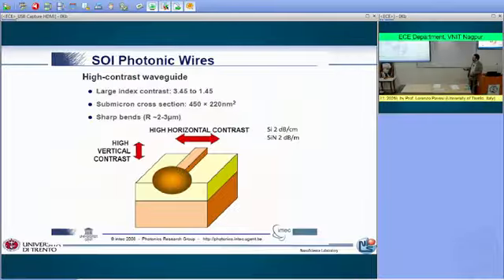Sidewall losses scale with the refractive index contrast. Okay, the larger is the refractive index, the more scattering you get out of the waveguide. So if you have a roughness of a few nanometers with silicon, since you have this kind of index contrast, you have a huge scattering loss. But in silicon nitride, you have the same nanometer size, but since the refractive index of silicon nitride is 2, you have a much reduced scattering. And this is the reason why, by using the same process, which means by using the same lithography process, you can get a much better propagation loss for silicon nitride than for silicon.